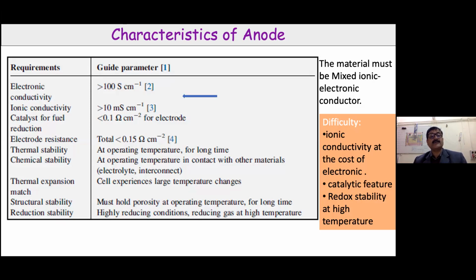Thermal stability is very important, and not only thermal stability but thermal compatibility of the anode and cathode is required, because the cell operates at very high temperature in the range of 600 to 1000 degrees Celsius. If one material has a larger thermal expansion coefficient than another, cracks will be generated, and that leads to problems in the operation of a solid oxide fuel cell. So when you choose a material, you have to think in this direction also: anode, cathode, and electrolyte should have almost the same thermal expansion coefficient. These are the properties of the anode materials.